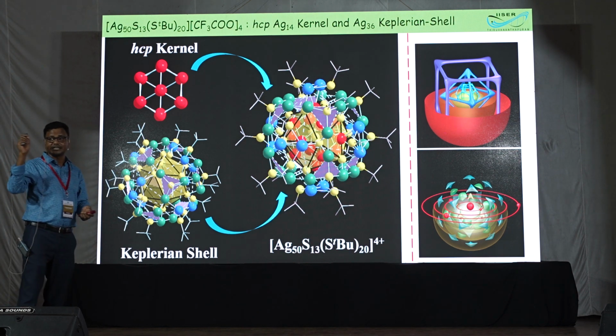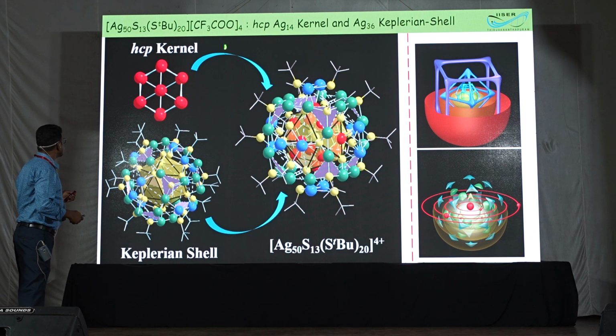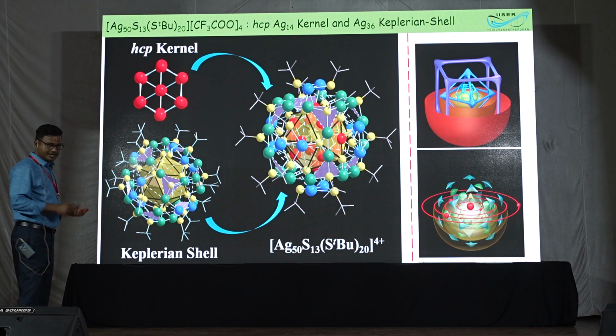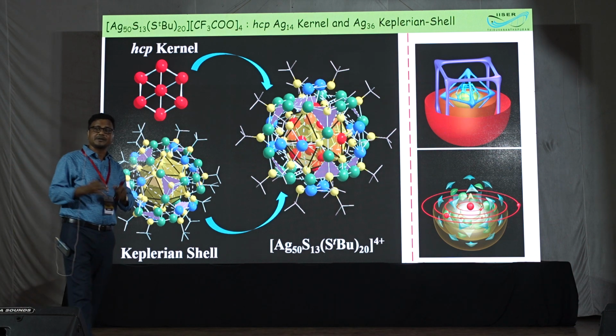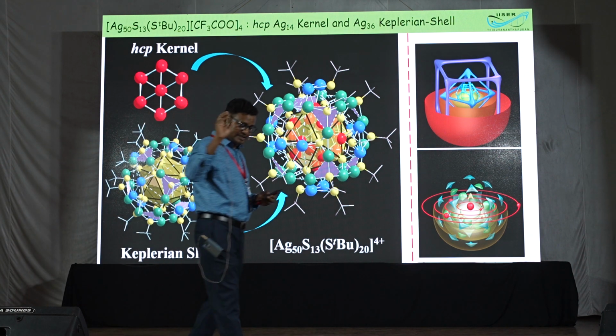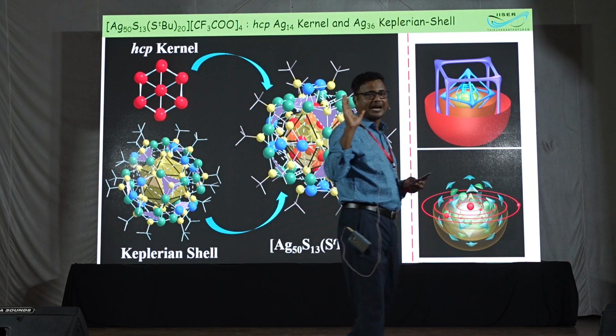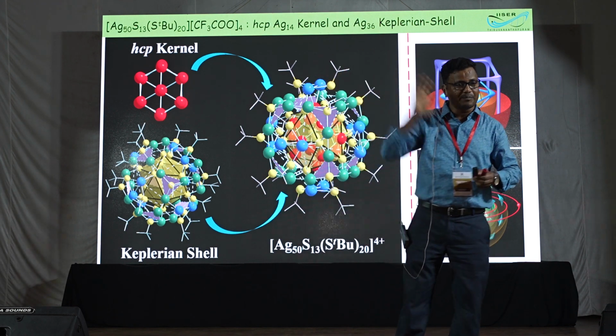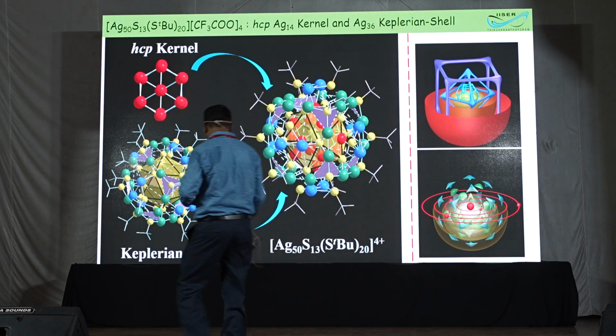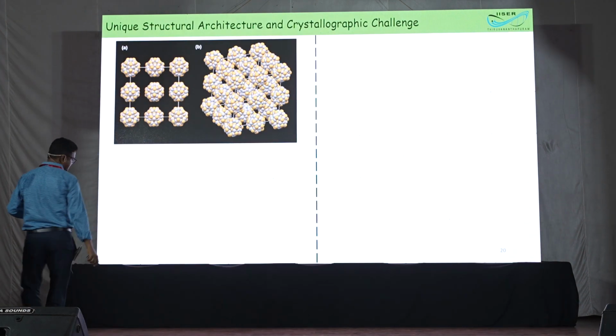As I mentioned, the difficulty is in the structure. We can see that this one we can detect crystallographically, but this is not. The reason is very simple. Crystallography depends on how many electrons. X-rays are diffracted by the electron density of the atom. Silver is very heavy compared to carbon, so that's why carbon is not visible, because we didn't have a good crystal structure.